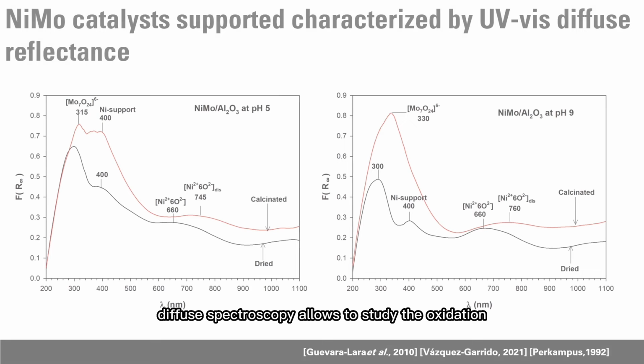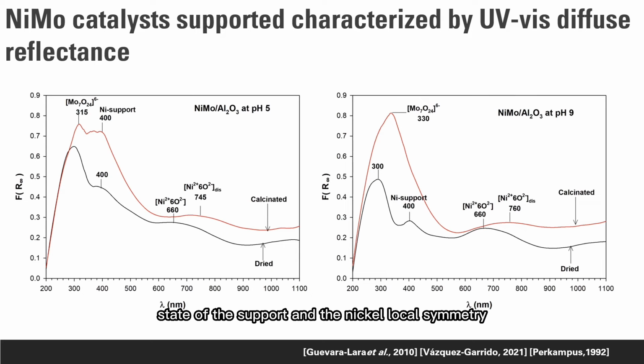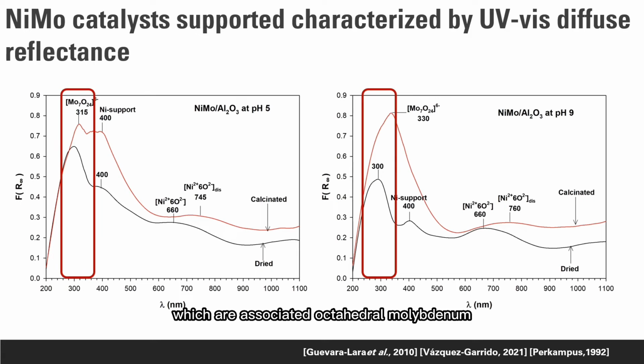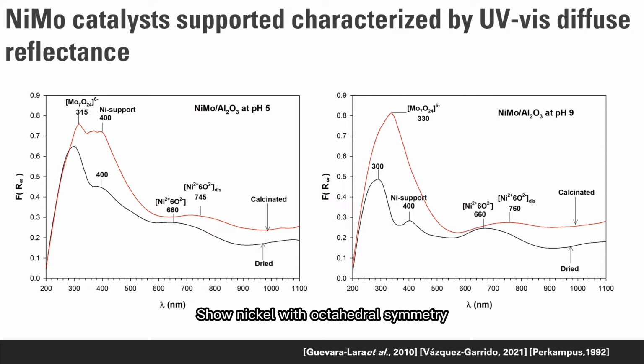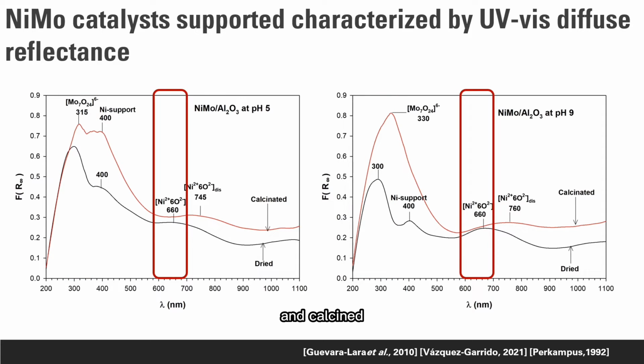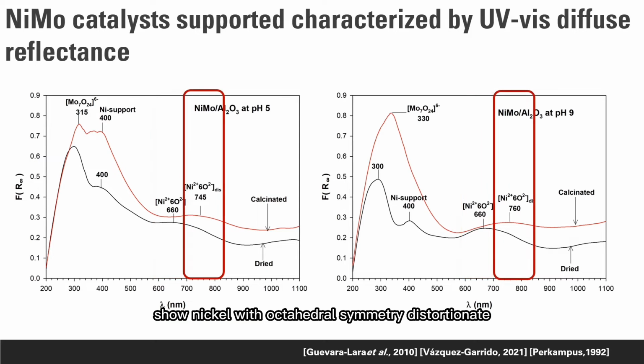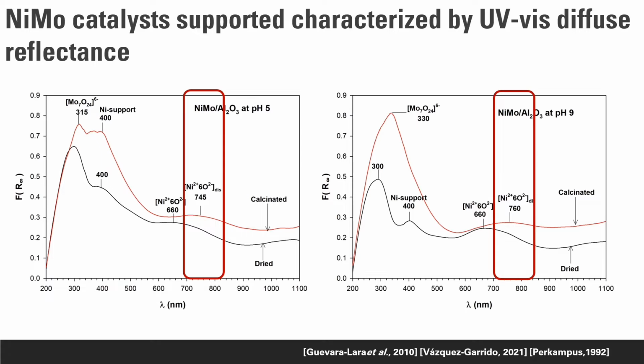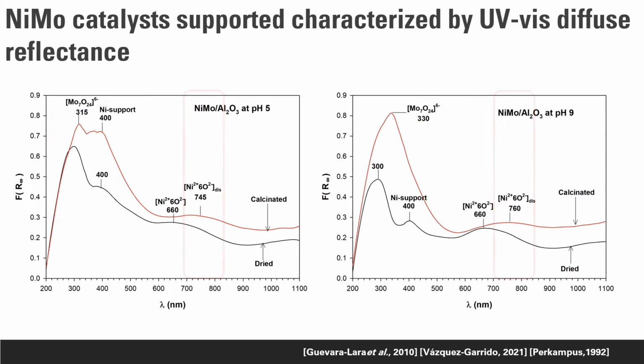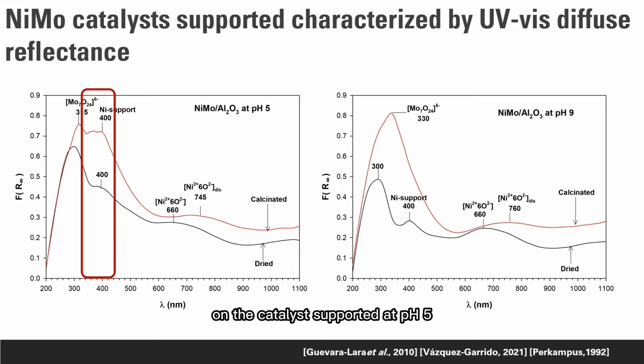The diffuse reflectance spectroscopy allowed us to study the oxidation state of the support and the nickel local symmetry. The UV-Vis-DR spectra of nickel molybdenum alumina at pH 5 and pH 9 exhibit bands which are associated with octahedral molybdenum. The dried catalyst showed nickel with octahedral symmetry, and the calcined catalyst showed nickel with distorted octahedral symmetry. The catalyst supported at pH 5 has increased nickel-alumina interaction, hence low catalyst activity.